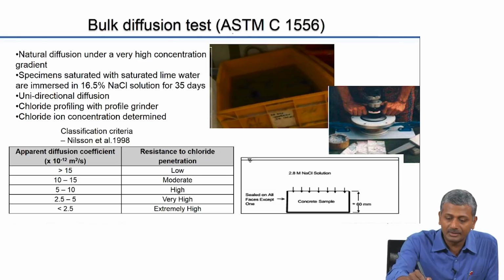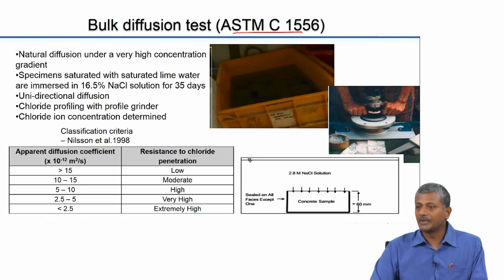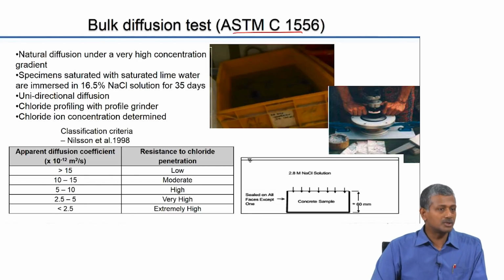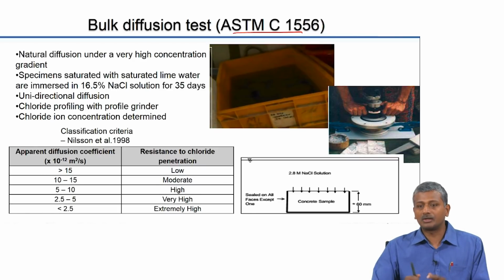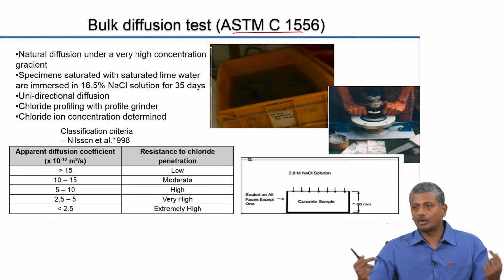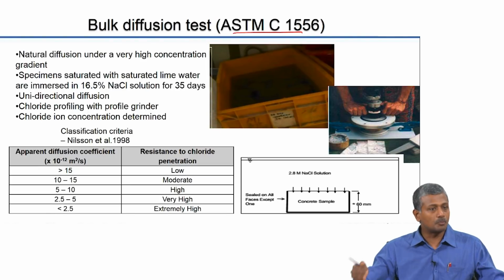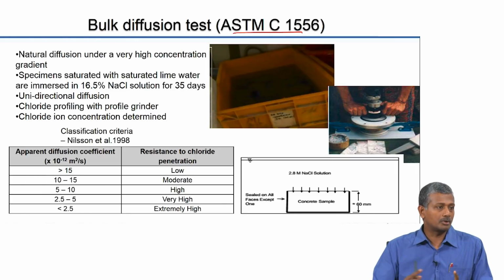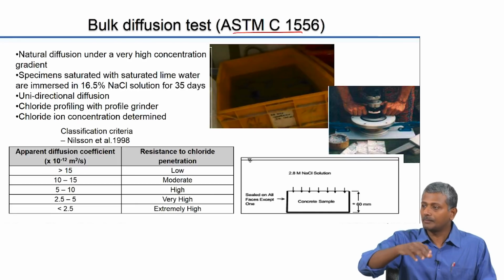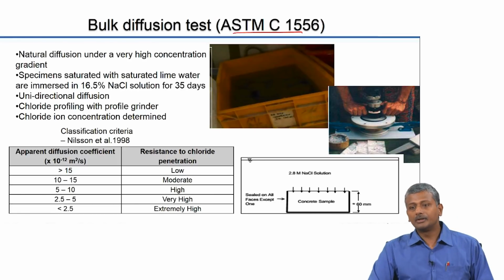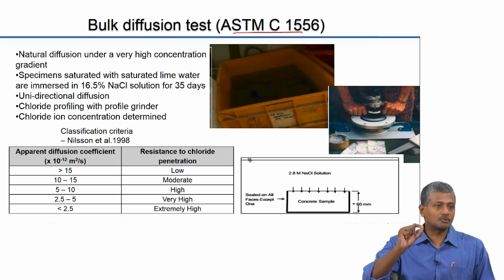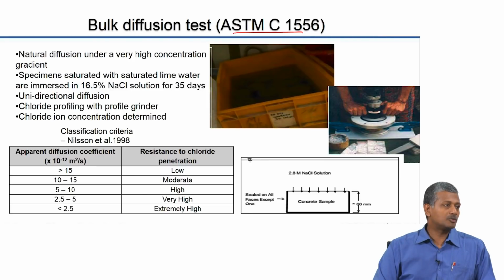This is covered in a standard, ASTM C1556. It's also known as a bulk diffusion test. The older version of the bulk diffusion test was a ponding test in which you had to actually create a slab of concrete and put sodium chloride solution on the top. That means you pond the sodium chloride solution on top of the concrete. But then the process is similar. You need to take cores through the concrete from time to time and determine the chloride profile. That means the extent of chloride concentration along the depth of the concrete.